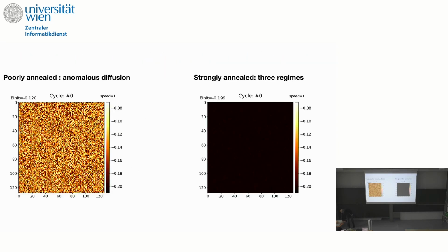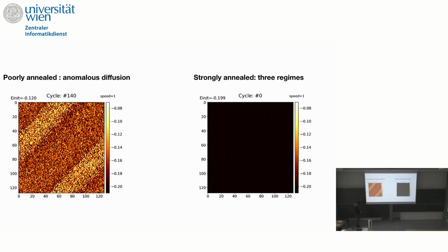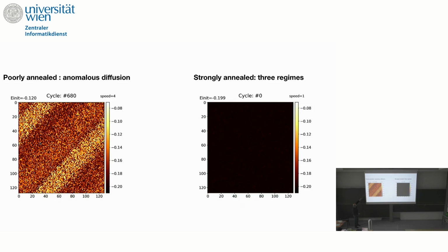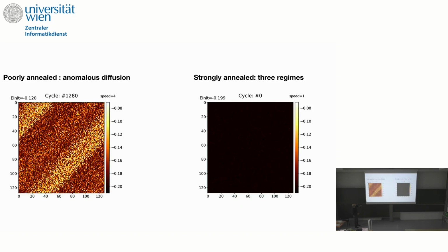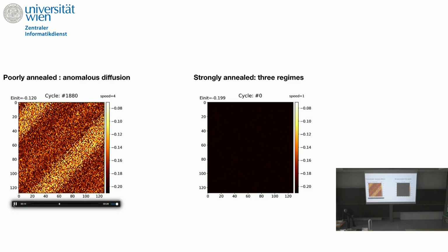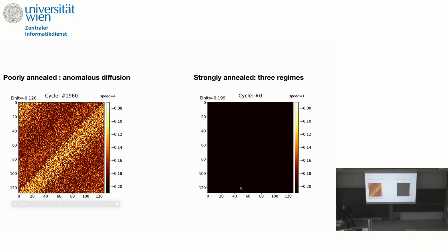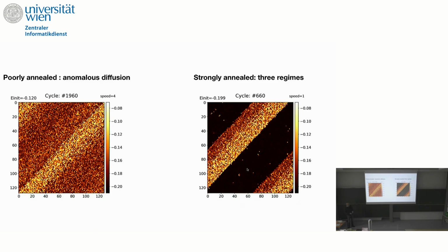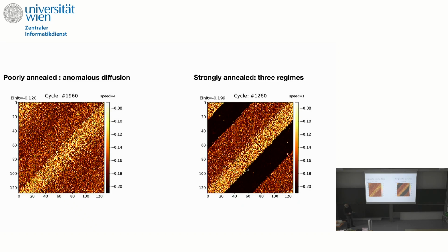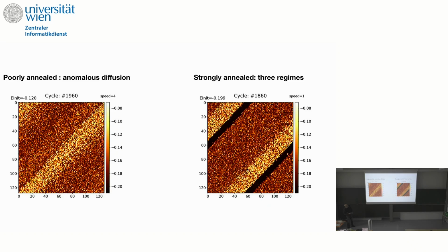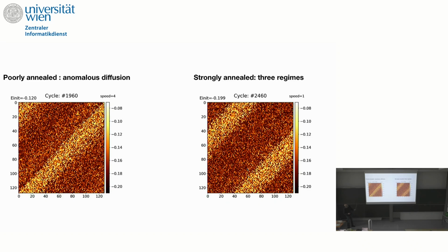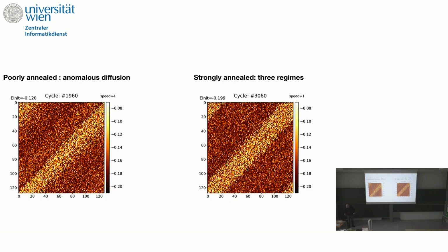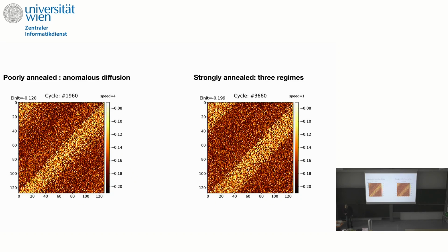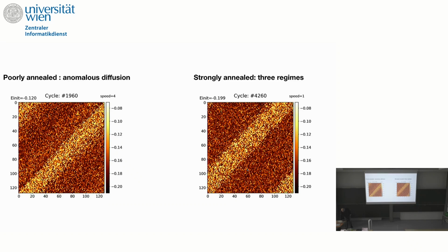So let me show. This is the poorly annealed case. You have the shear band, and during the different oscillations it moves a little bit back and forth, and it diffuses, okay? Now, if you start from a very fragile sample, what you should observe is that the shear band first grows, reaches its size, and then moves ballistically. Let's see. So it grows, moves ballistically, always in the same direction. This is because the solid is so much annealed that it invades. And once there is no more black region, then it starts to diffuse, okay? And this is what we see in our simulation. We tried to understand why, but we were not able to give a clear answer.